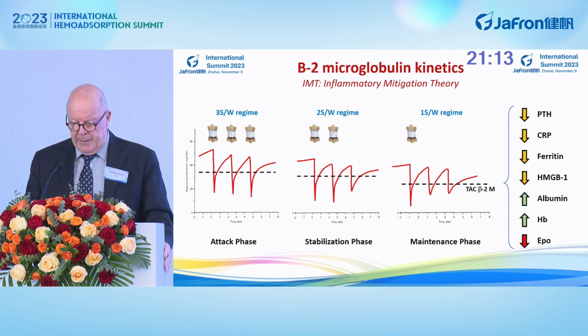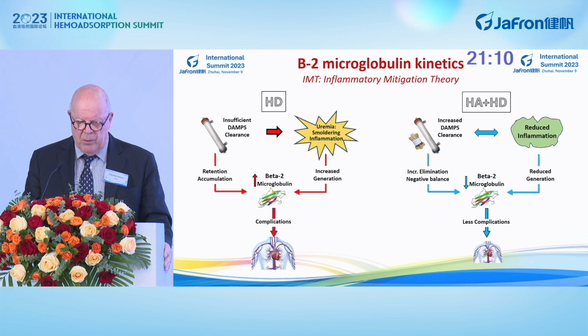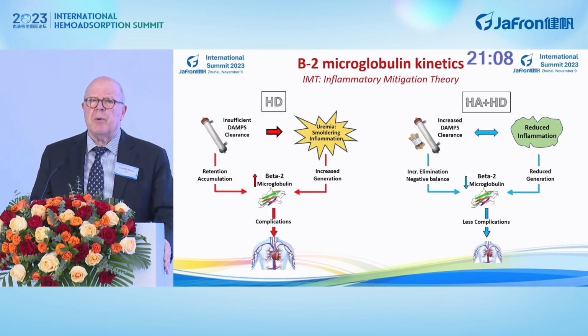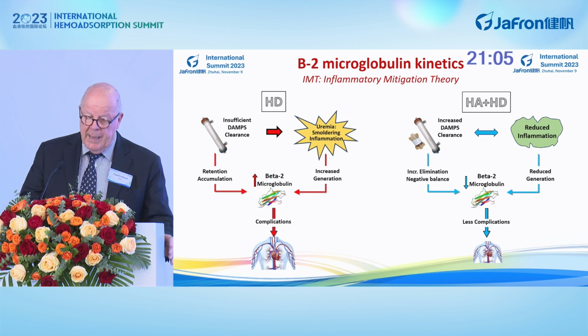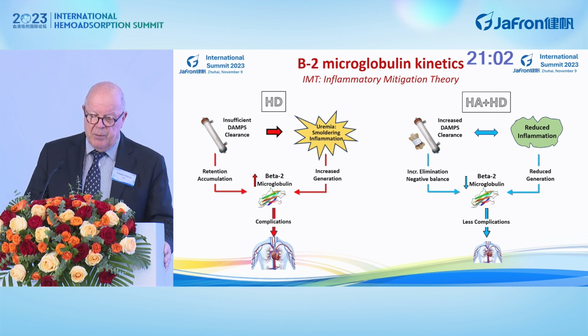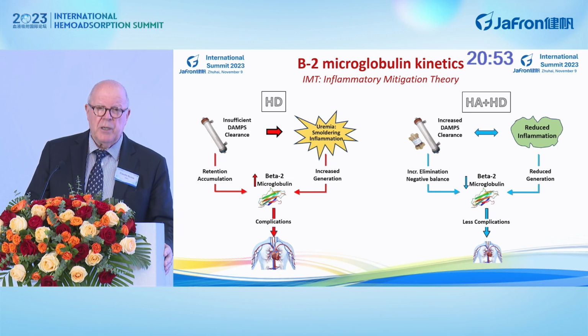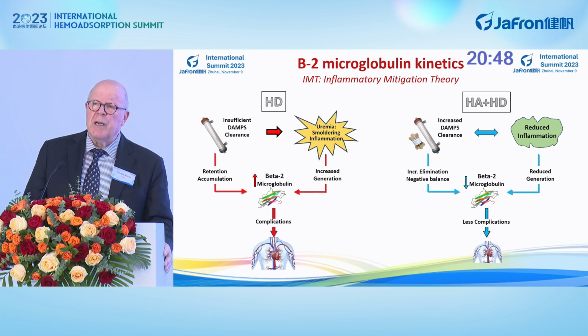Now, the theory that I have put forward for this response is the following. Not only do you remove, in dialysis, you have insufficient removal of beta-2, but also you have a smoldering inflammation that may lead to an increased generation of beta-2 microglobulin and increase the complications. In hemoadsorption plus hemodialysis, not only do you remove more beta-2 microglobulin, but you also remove part of the inflammation, leading to a reduction in the generation of beta-2 microglobulin, which may be a new interesting paradigm.